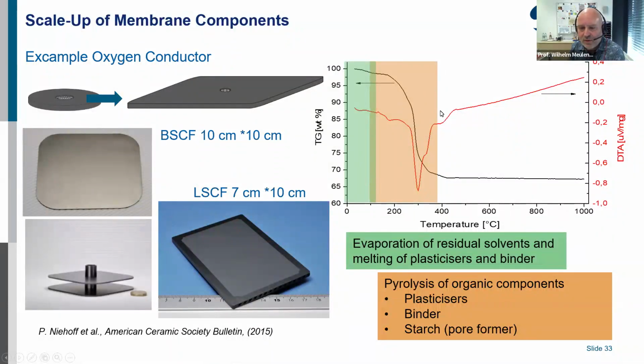And then once everything of this organic is removed, we can go faster to higher temperature, to our final sintering temperature, which is, for example, for BSCF 1100 degrees C. For LSCF, it's in the range of 1150 to 1200 degrees C. Or if you now look to the barium zirconates, where Pati is working with, you can also find temperatures up to 1700 degrees C. So also here, it depends on the material.